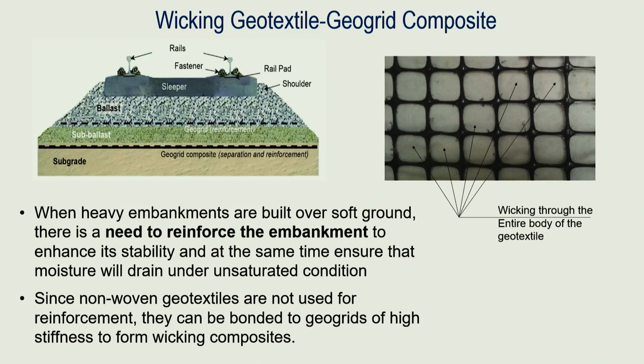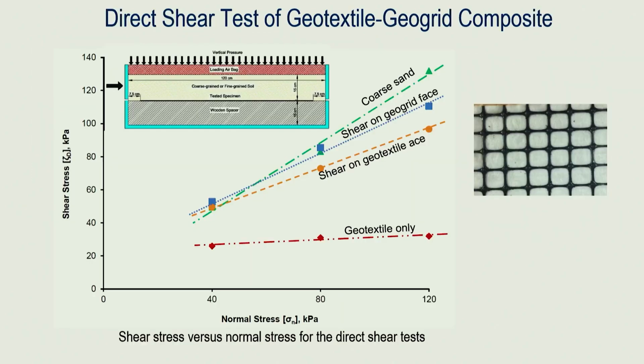And this is an example here of a direct shear test that has been performed on one of these materials. And the idea is to try to identify where exactly this material fits. Would the resistance fit near the geotextile only, or would it fit near the core sand, which would be the upper limit? So we have now a lower and upper limit, and interestingly enough this material seems to perform reasonably well as far as the interlocking ability, depending on which plane you're shearing the material against. So if you shear the material, for example, against the geogrid, you get a higher friction angle.